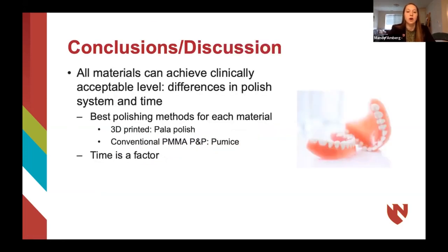In conclusion, we found that all denture materials can achieve a clinically acceptable level of polishability, but differences are found in what polish system works best for each material and the time spent polishing. All 3D printed materials achieved overall better polishability when polished with Pala polish. In contrast, conventional PMMA lab fabricated materials achieved overall better polishability when polished with pumice.